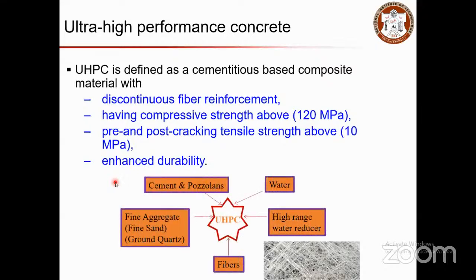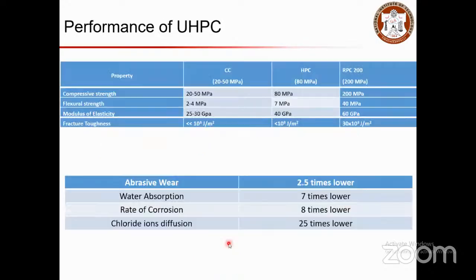So adding fibers will help to bridge the cracks, and that will help you to enhance the toughness of the material. So that's why a combination of these things will help you to achieve ultra high performance. Typically here you can see it's a combination of cement and pozzolans, water, and of course here the water. To achieve the high strength, the water cement ratio will be lesser, so you need to go with high range water reducers and fine aggregates. So you typically reduce the coarse aggregates when you need to go with high performance concrete, and then add the fibers to improve quality.